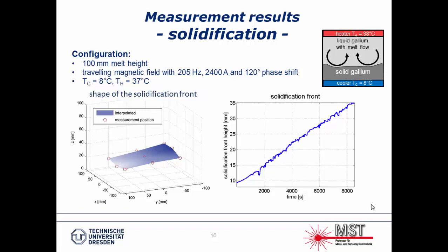Just to show an example of the measurement, how the solidification front progresses over time. For the solidification process, we have the height of the solidification front plotted over time. After about 2 hours, the solidification front has grown about 25 millimeters.